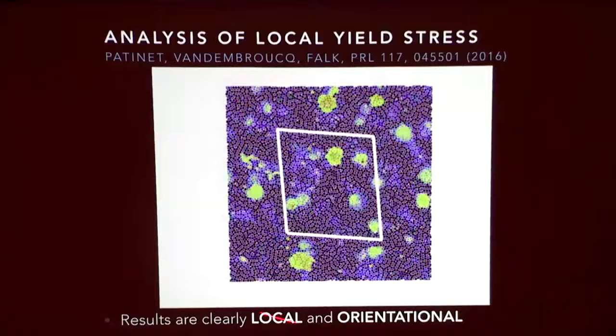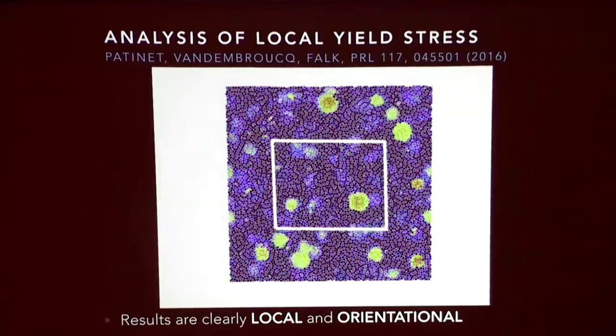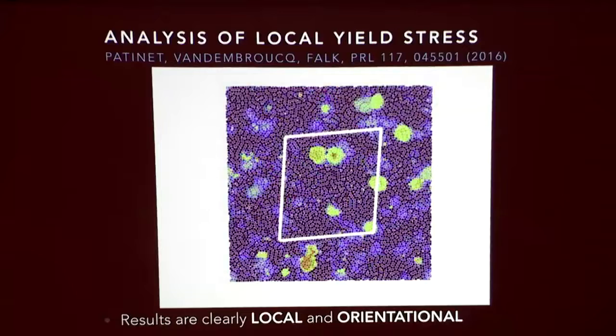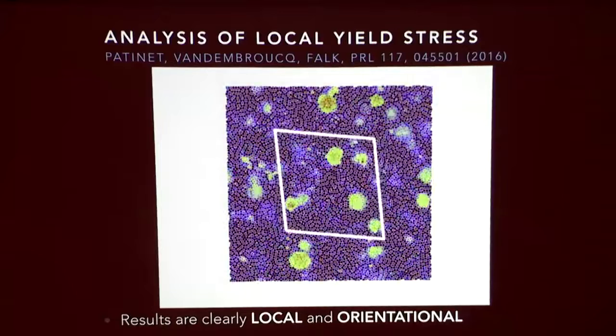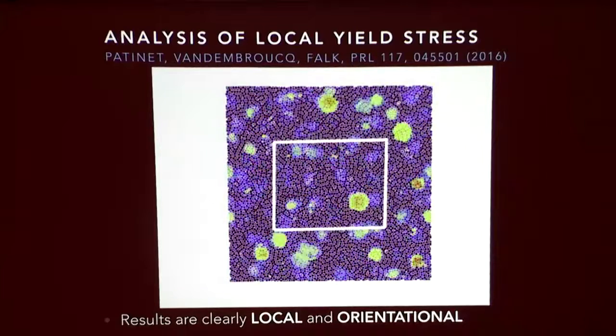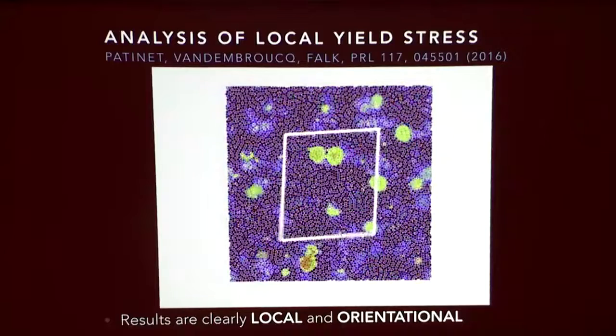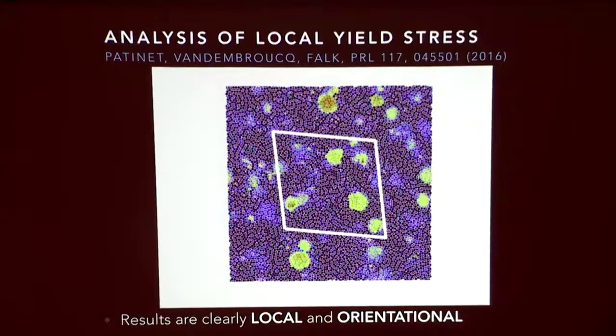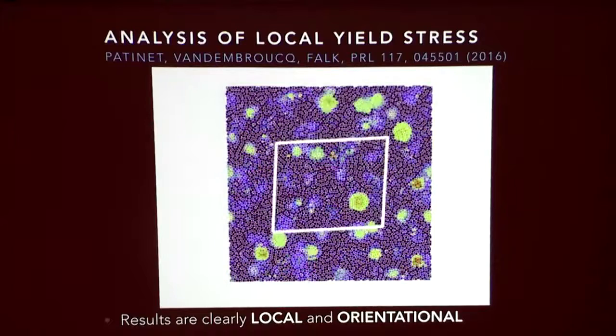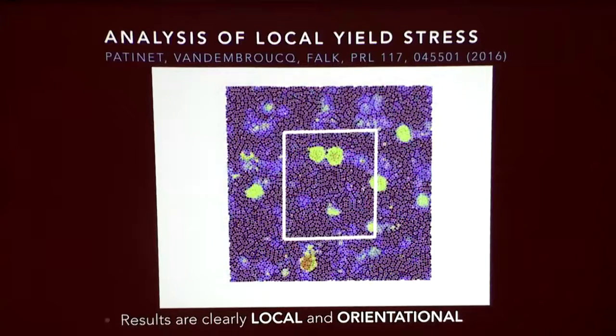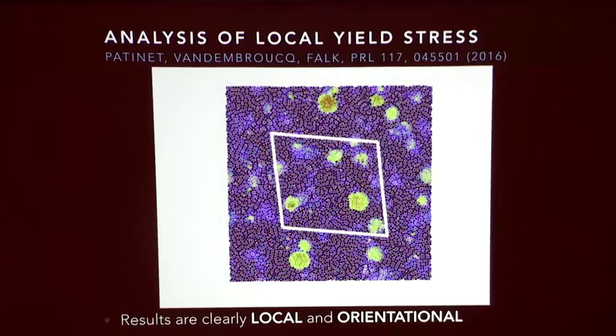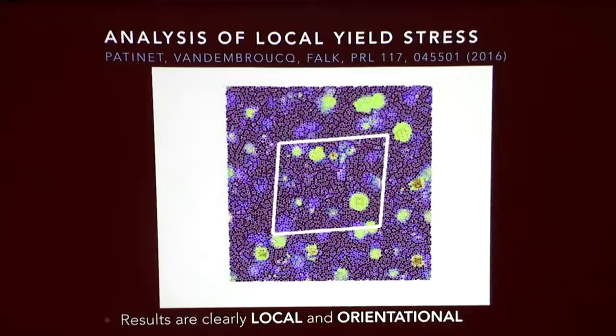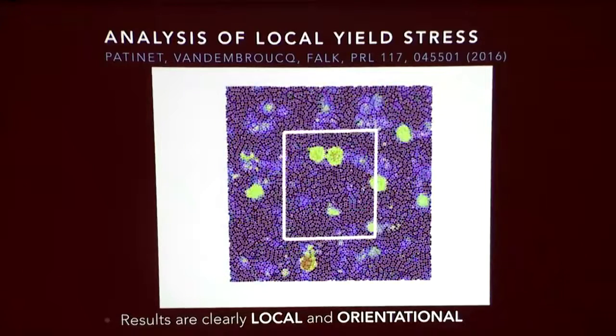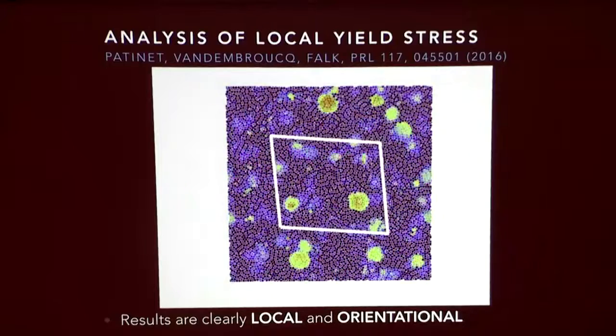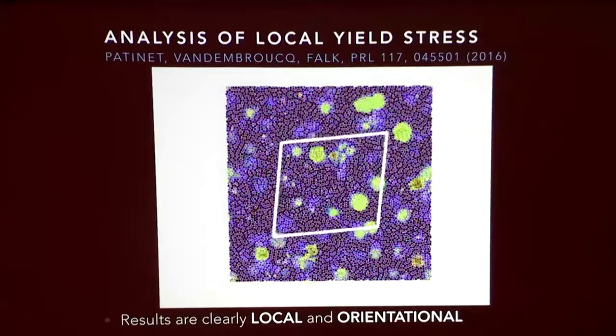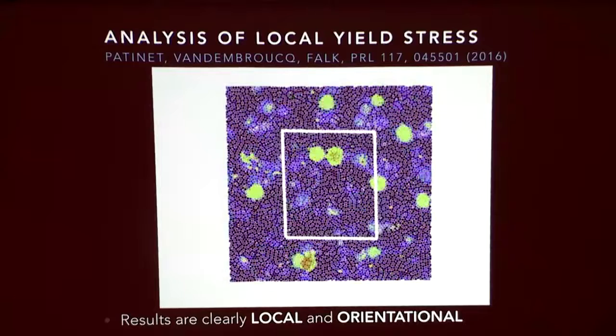One issue that comes up in the metallic glasses literature is this idea that you can describe the local structure through something like a free volume, the idea that density must control the behavior of the system. But density is a scalar quantity. If free volume were the only piece that was interesting, then you'd expect that if something has high free volume, it's as likely you could deform it in any direction. There's nothing about free volume that picks out direction.